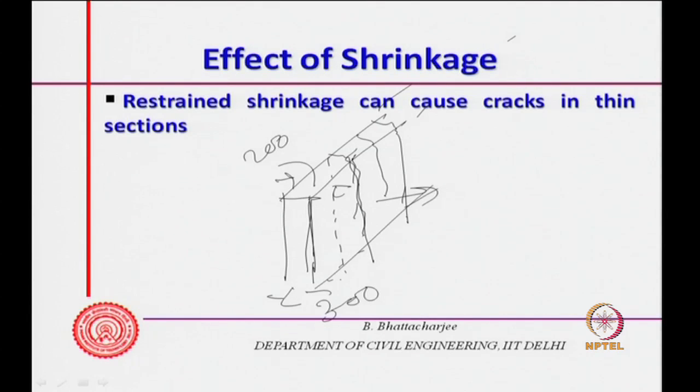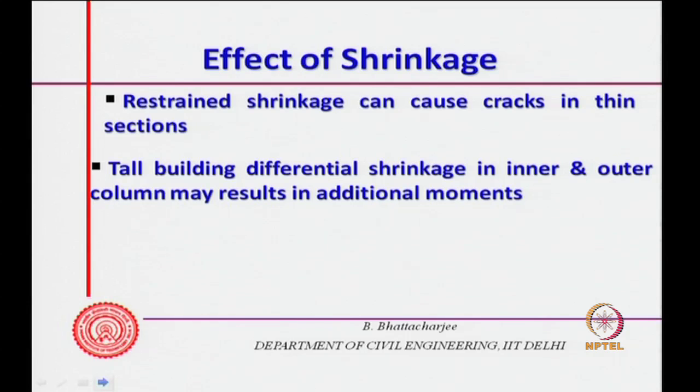This is a phenomenon seen in northern India, especially when you cast the concrete around May, June, when relative humidity is very low, 10 to about 40%. If curing is not done properly, this can result in cracking, and these cracks you see normally within 2 to 3 months of construction. Drying shrinkage cracks are fairly common. High strength concretes are susceptible to autogeneous shrinkage because you have a lot of cement paste in the system, and therefore they may be susceptible to shrinkage.